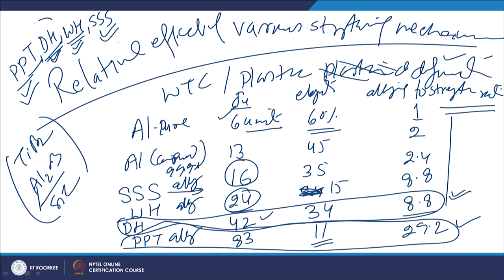So, whenever there is a loss of precipitates or the dispersoids present in the aluminum alloy, the effectiveness of the work hardening or the solid solution effect is limited. That is why we will notice, either during fusion welding or due to deformation, that loss of precipitates or loss of the dispersoids will lead to softening. So, despite the refinement and the solid solution strengthening, in the case of precipitation and dispersion hardening alloys, there is a loss of strength and loss of hardness. So this is the net effect for the aluminum alloys and the magnesium alloys, which are precipitation strengthened.